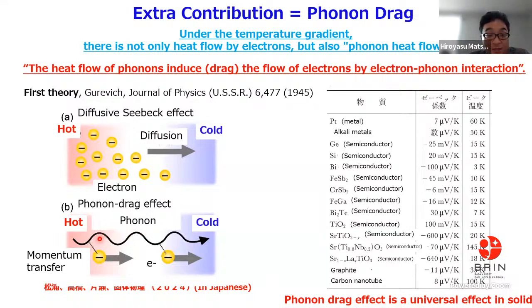So if we have the heat current of phonons, and when we use the interaction between the electrons, in this case we have an additional electrical current like this. So the heat flow of phonons induces the flow of electrons by electron-phonon interactions. This is the phonon-drag effect. The phonon drag is a universal effect, because there are many materials that show the phonon-drag effect. This is the metal case, this is the semiconductors, and metals, graphite, carbon nanotubes also show the phonon drag.